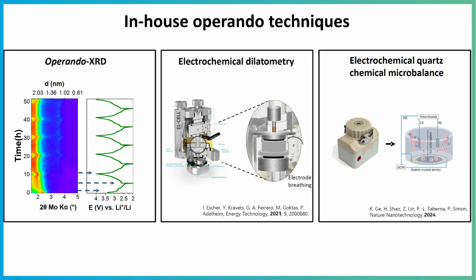And for this, we made use of our in-house operando techniques. We made use of operando XRD first to track the changes in the interlayer spacing during cycling. Then we made use of electrochemical dilatometry. This was done to measure the electrode swelling on a macroscopic level. And lastly, we made use of quartz crystal microbalance, the EQCM, which detects whether the lithium ions are intercalating alone or along with the solvent molecules